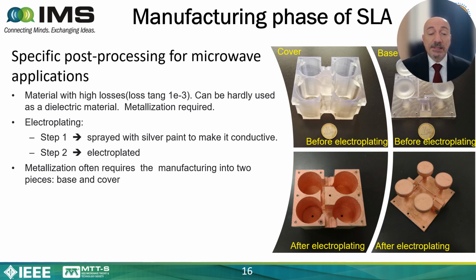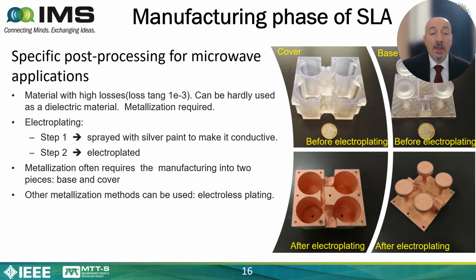Okay, unfortunately, metallization often requires the manufacturing in two pieces, a base and a cover, because you have to metallize the internal part. So you have to divide, of course, in two pieces and then assemble it. And indeed, we have the cover before and after the electroplating, as well as the base before and after the electroplating. Once you have electroplated, you can just assemble the two parts. Of course, other metallizations are also possible, for example, the electroless plating. In this case, by using electroless plating, you can also obtain monolithic manufacturing.